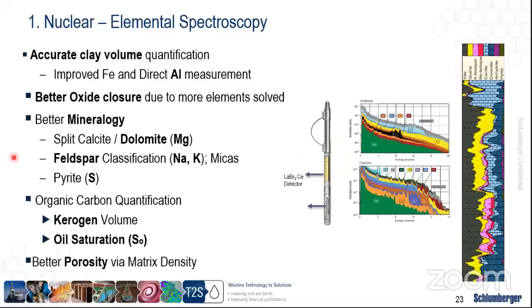This is very important when it comes to analyzing unconventional reservoirs or complex lithologies that we have in, for example, here in Egypt, the Gulf of Suez. So it comes into play because we can accurately measure the clay volume directly from the tool, and then we can solve the sand, pyrite, limestone, and dolomite. And this is very important when it comes to a proper formation evaluation, because the more accurate the volumes that we have, the better the estimation of the porosity. And this would severely affect the oil in place equation calculation when it comes to reserves estimation.